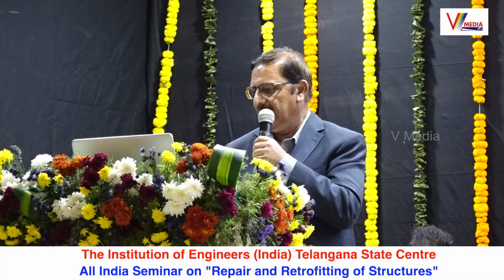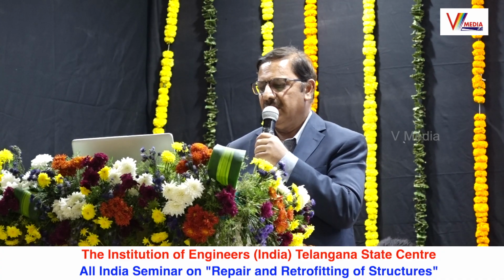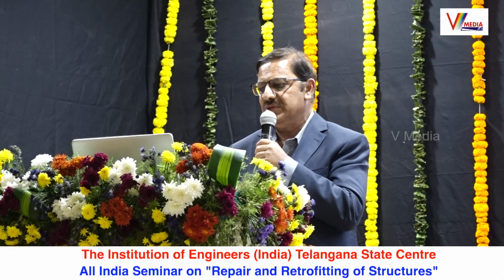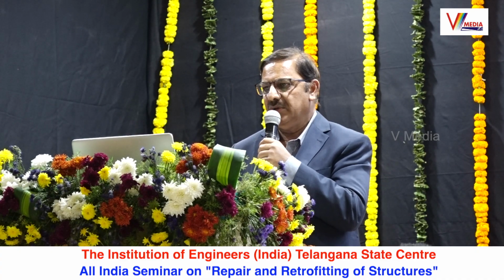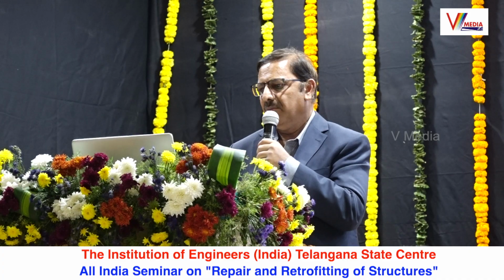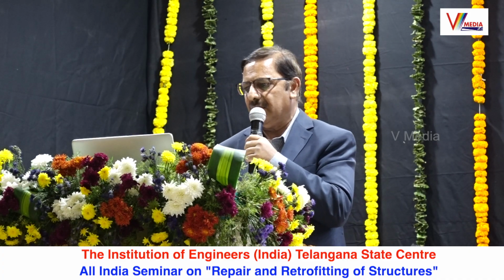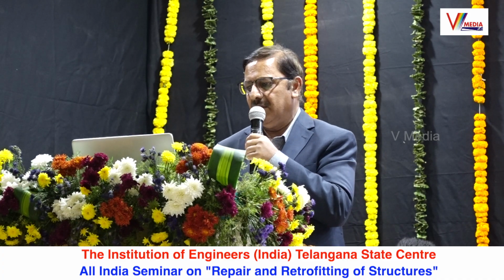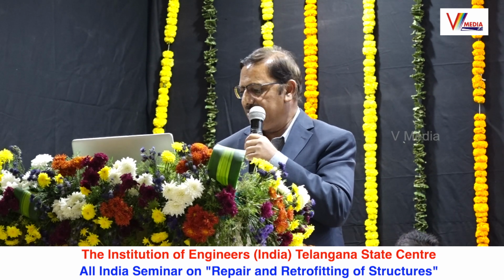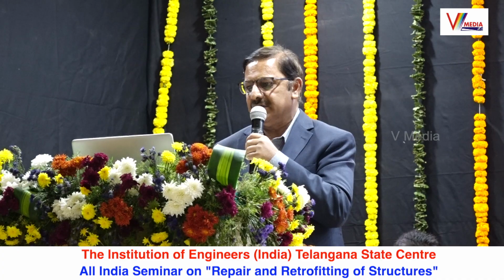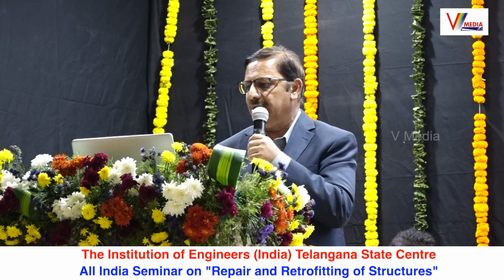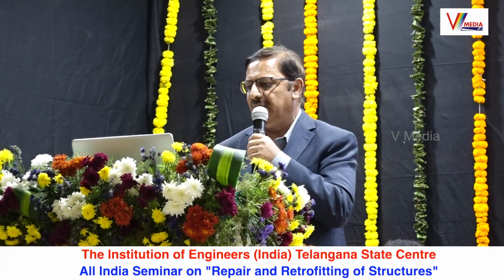The most commonly used is the zinc anode, and the advantages are that it is easy to install, cost effective, and there is no need for maintenance, just install and forget. But there are limitations: they provide limited current due to the limited anode material available, and therefore they are applicable to smaller structures. This is the anode which is commonly used and commercially available in different weights, 40 grams to 330 grams.